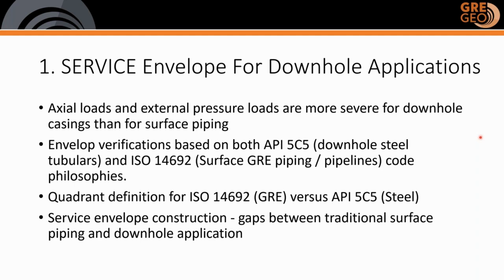The envelope verifications are based on both API 5C5, which is focused on downhole steel tubulars, and ISO 14692, which is used for surface GRE piping and pipelines. The verification of pipe plus connector for casings is much more challenging than for piping and pipelines. Steel casing connectors are verified according to the API as indicated, and this is quite different and much more severe than specified for ISO 14692. Furthermore, in the service envelope construction, we found that there are gaps between traditional surface piping and downhole applications, and that is something we had to address.